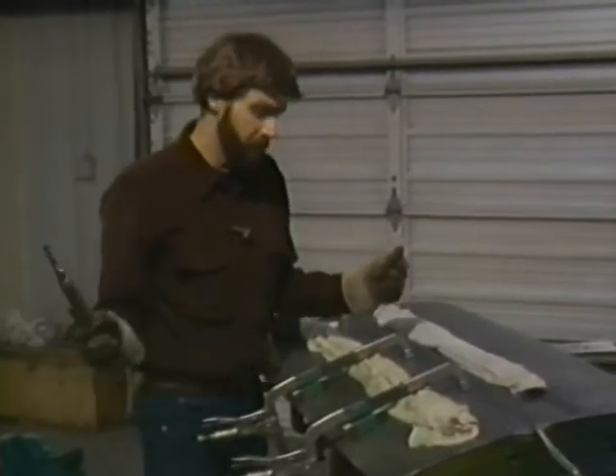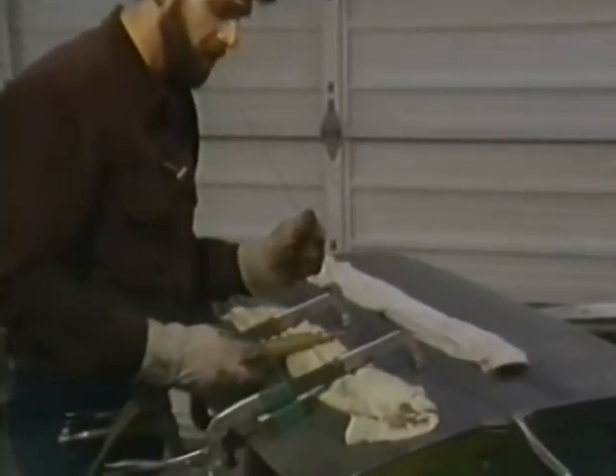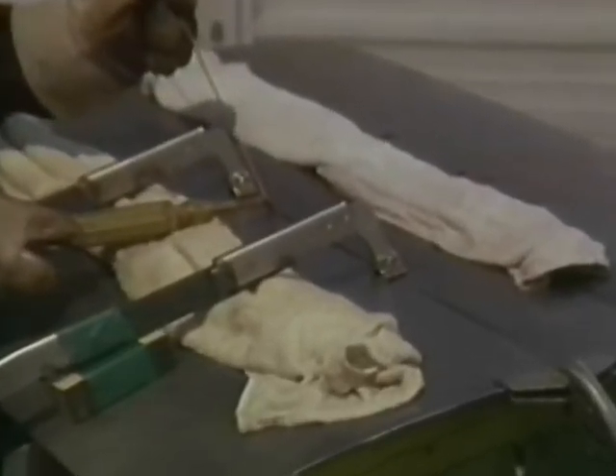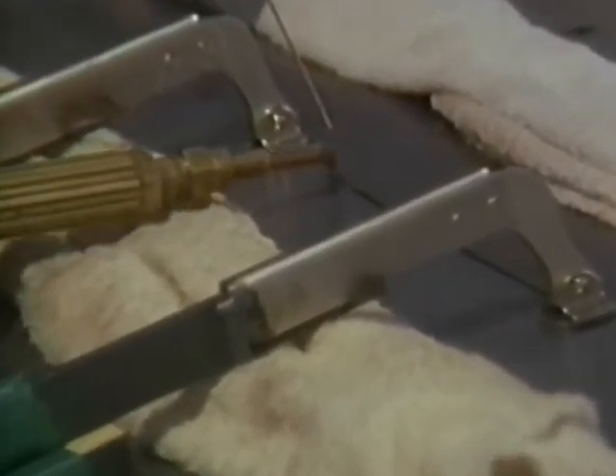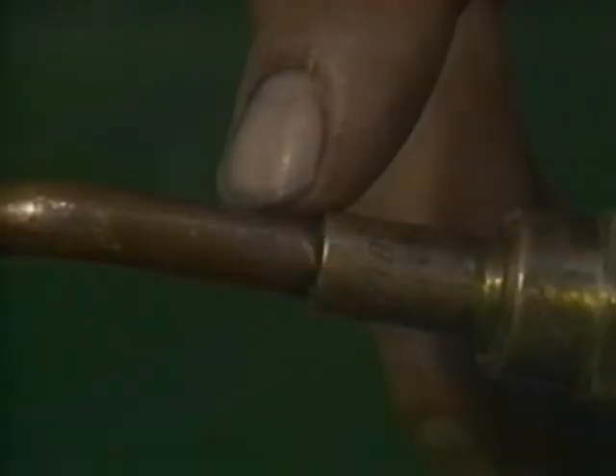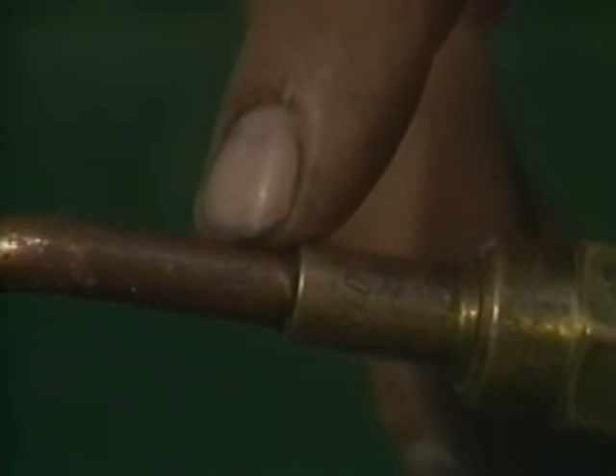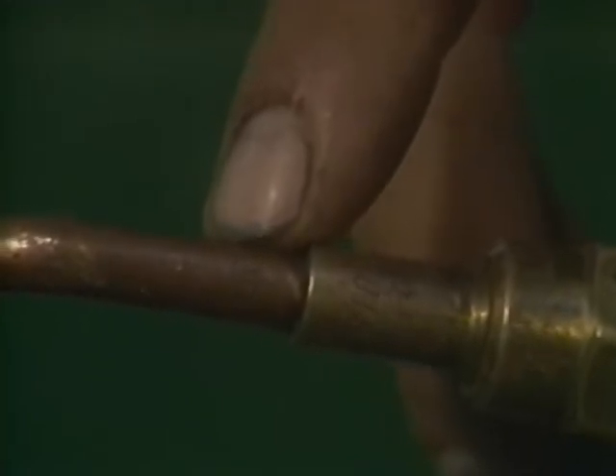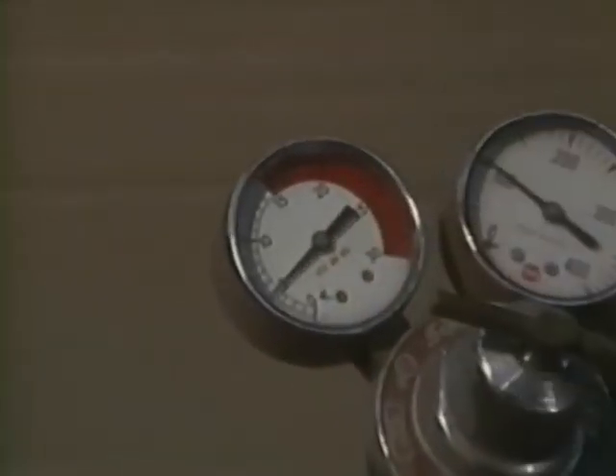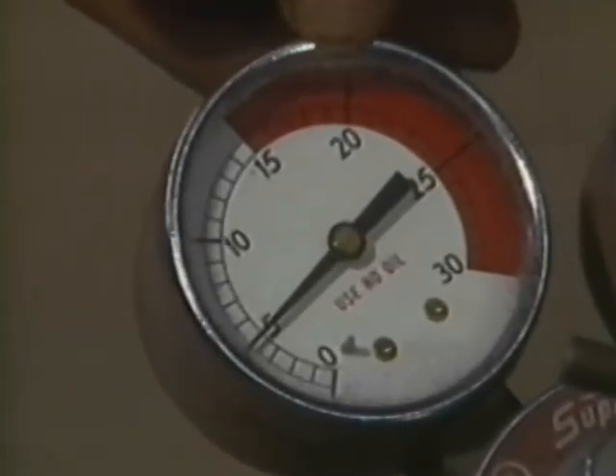While I'm tack welding, I've always got a filler rod ready, just in case the metal starts to burn away rather than fuse together when I put the torch to it. The torch tip size I like best for hammer welding is size 00. For gas welding, I wear these thin leather welding gloves, and we use a 1/16 inch copper-coated steel gas welding rod. The acetylene regulator is set at 5 pounds pressure, and also the oxygen regulator is set at 5 pounds pressure.